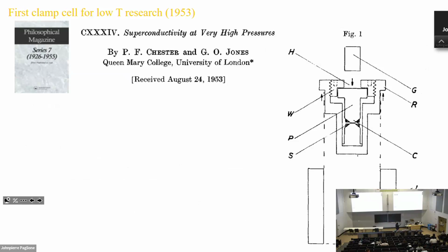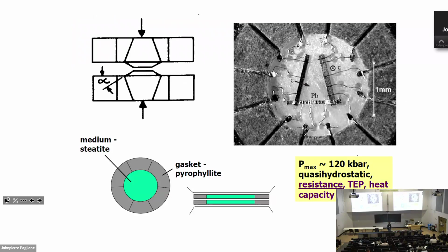So here's the Bridgman anvil cell. You still squeeze the cell at room temperature. Once you squeeze, then you use a screw to screw it down and lock the pressure. It's only that simple. But this is a really important progress in the field. It took almost 20 years between the Bridgman cell and the low temperature Bridgman cell. So at the time, the first clamp cell actually is a clamp Bridgman cell. It's not the piston cylinder cell. So let's talk about this Bridgman cell a little bit.